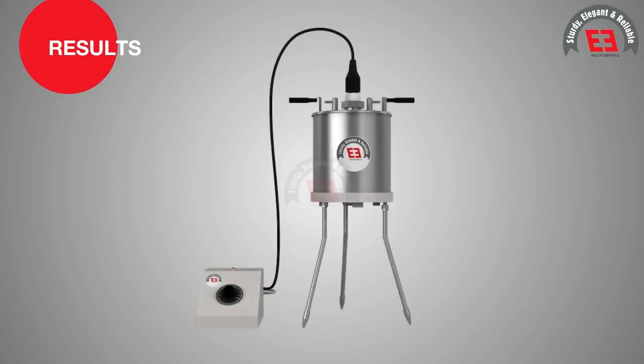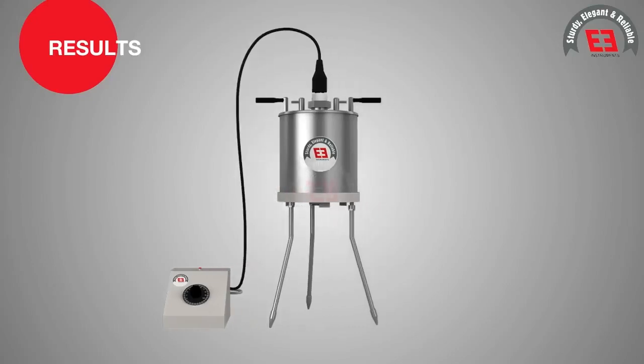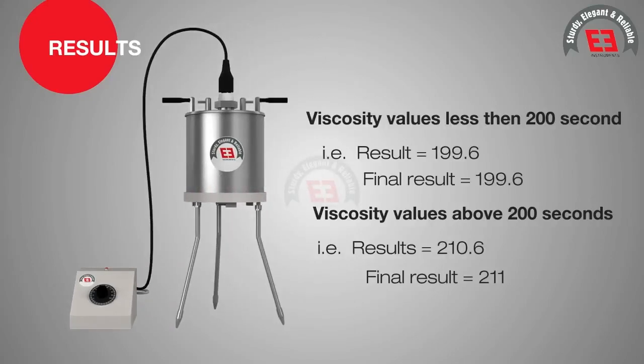Results. The Saybolt Furol viscosity of the bitumen emulsion is recorded in seconds, correct to 0.1 second for viscosity value less than 200 seconds and to the nearest whole second for values above 200 seconds.